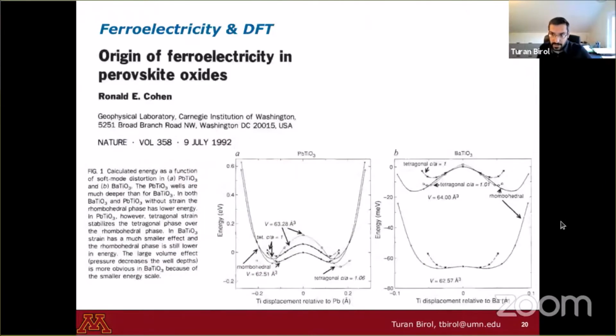Now, one of the early successes of DFT, and when I say early, I'm talking about early 1990s, so that says something about my age, I guess. But one of the early successes of DFT was to actually reproduce these double well potentials for the first time. So this is a Nature paper from 1992. This is something now a PhD student can learn how to do in a few months. In lead titanate and barium titanate, 2 well-studied ferroelectrics under different boundary conditions, Rabe and Cohen had shown this double well potential and showed that these first principles methods, these methods like DFT, which start from the Schrodinger equation without any fitting parameters to experiment, can really reproduce ferroelectric properties of materials.